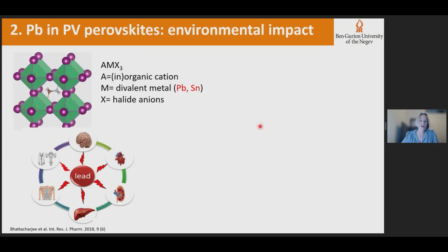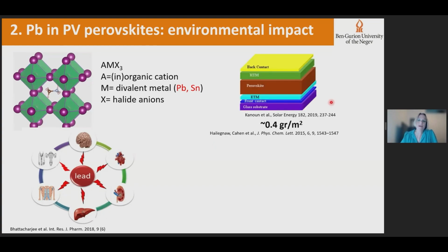Another aspect, which I will just touch on very briefly, is the presence of toxic metals. Lead is, of course, very concerning. Tin is also not a very fun metal to work with. They are both very toxic. And if you calculate in the typical perovskite structure, there's about 0.4 grams per meter square, which is orders of magnitude larger than the acceptable limit of lead in electronic structure.